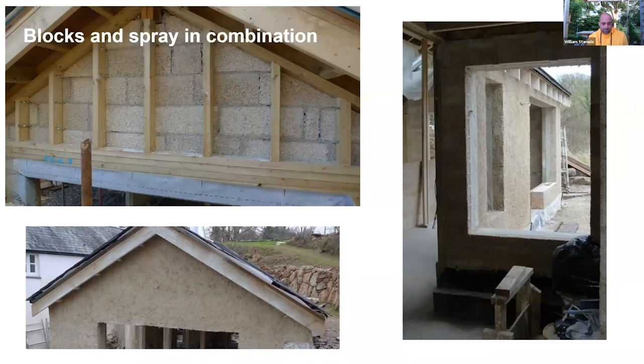This is a recent build I did in Dartmoor, where we used hempcrete blocks as the internal permanent shuttering, and then sprayed from the outside. This gave us the instantly dry internal environment to plaster straight away, coupled with the air tightness and speed of construction that sprayed hempcrete gives you. So as soon as we finished spraying, the windows could go in and we could get on with the plaster inside while the sprayed hempcrete dried to the outside.